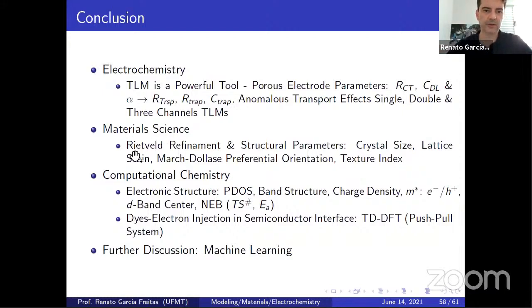In material science, we can use Rietveld refinement to obtain structural parameters, crystal size, lattice, using March-Dollase preferential orientation. Using computational chemistry, we can obtain DOS, PDOS, band structure, charge density, the effective mass of electron and hole, the band center, using NEB, and use TD-DFT to study dye injection on the semiconductor, especially for the division one, isn't it? Especially using push-pull dyes as well.